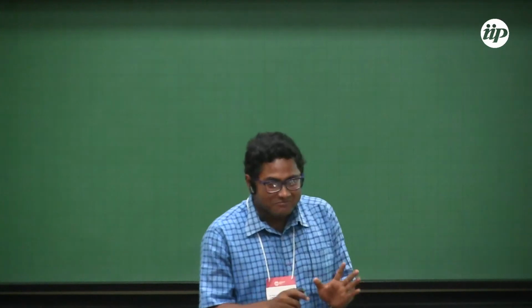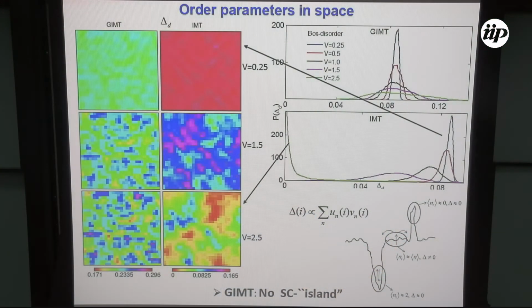So yeah, I should have been careful. I'm actually talking about no Gutzwiller approximation now. So this IMT, I should have made it clear. IMT is no Gutzwiller approximation. GIMT is with Gutzwiller approximation. If you do not have any Gutzwiller approximation, you will then form double occupancies. This is the explanation for the right-hand side of formation of superconducting islands. But interestingly, if you include strong correlation, as you were saying, you will not have these double occupancies. And then the nanoscale inhomogeneities behave very similarly. They will never form superconducting islands.